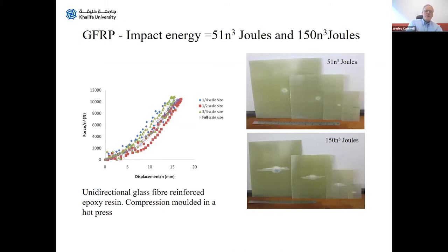So then we went on to other materials as well, such as a straightforward glass fiber reinforced plastic. This was a unidirectional GFRP. The nice thing about GFRP is it's translucent and you can see the damage within it. So you don't need to rush to your ultrasonic C scanner and these sorts of things. You can see the damage quite nicely after impact. So here we've got the usual scaled force displacement plots for the four scale sizes. And once again, you can see that the response is similar across the four scale sizes.